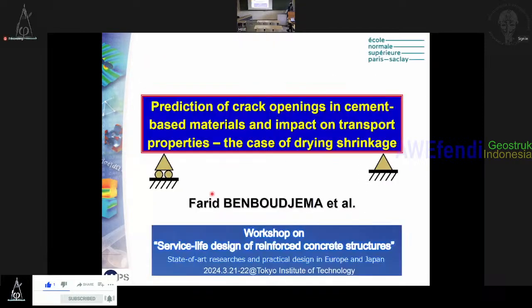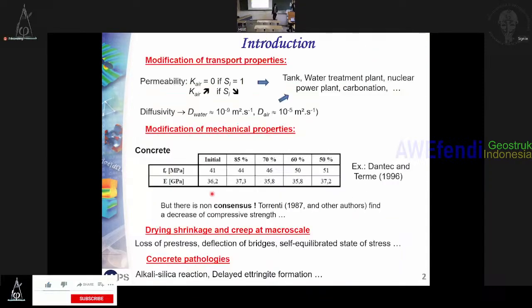Thank you. So if you look to the effect of drying, you will find that drying may have a positive effect or negative effect. So for instance, when we look to the permeability, especially the permeability related to gas, of course, the permeability is equal to 0 if the material is completely saturated. And when you dry the material, the permeability will increase. Sorry, I don't know if there is an echo somewhere. Well, I'm trying to find a place without echo.